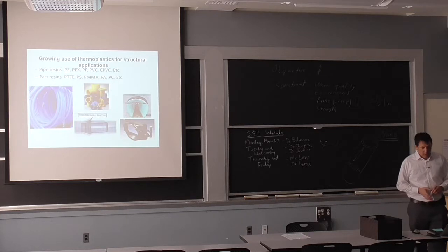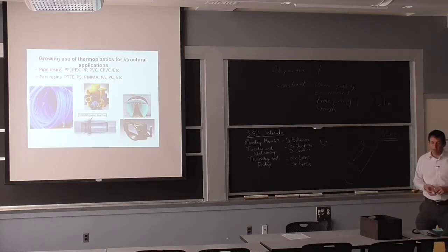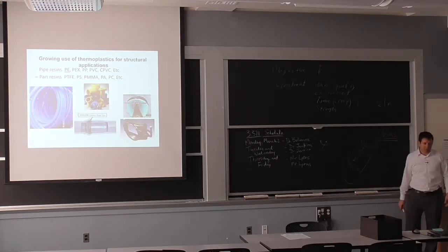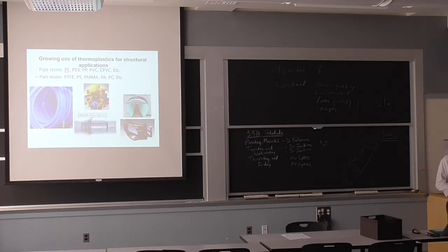So even though you have this issue of creep and viscoelastic behavior, we use a lot of polyethylene pipe for natural gas, for example. These are big pipes put underground, and they're supposed to last 25, 30, 50 years. The way you can do it is essentially put a big wall thickness and don't put a whole lot of pressure. So if you can afford putting the extra material to lower that hoop stress that we were talking about, then you're good for service. And I'll show some curves on how it actually works.